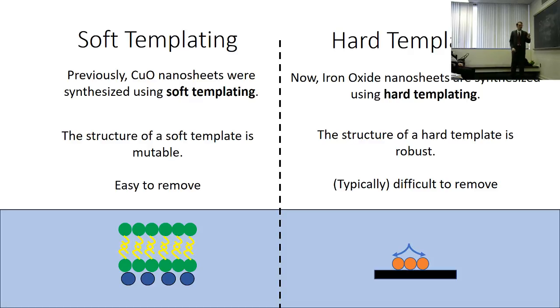Change your structure. However, if you notice, those things that change the structure of your soft template also affect the kinetics of your reaction. So it's really hard to study the kinetics of your reaction in these nanostructure syntheses. And it's also sometimes hard to get a particular nanostructure because you're changing two things at once, basically. Growth rate, growth parameters, and also structure parameters. And growth parameters affect structure parameters.